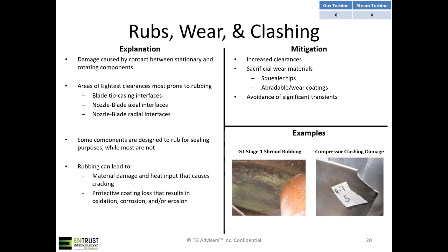Some of these components, particularly the blade tip and the case interfaces, are designed to rub a bit for sealing purposes. That helps keep your performance up, but most are not. Rubbing can lead to material damage, even heat input. A lot of times when you have two items that are rubbing together, heat will be dissipated into the material, and you'll end up with some level of cracking.